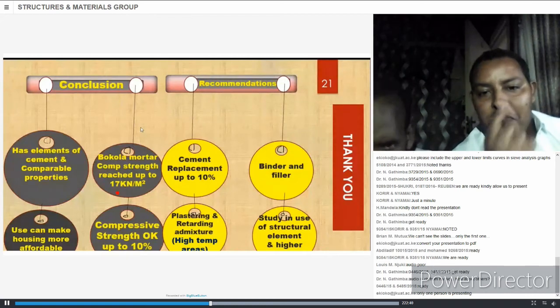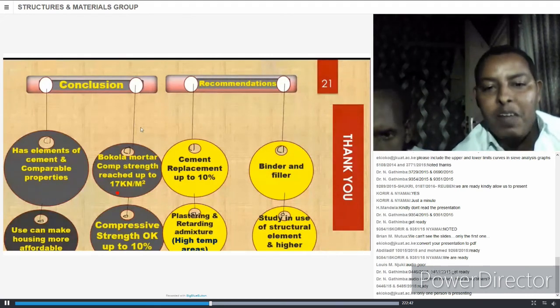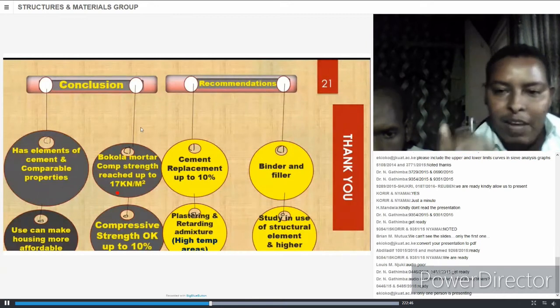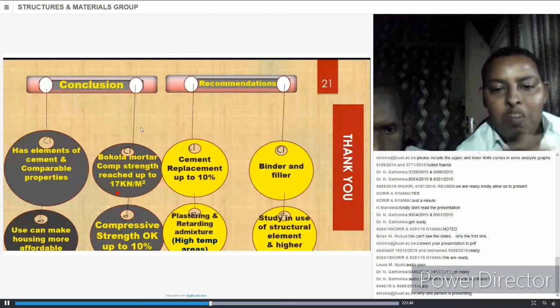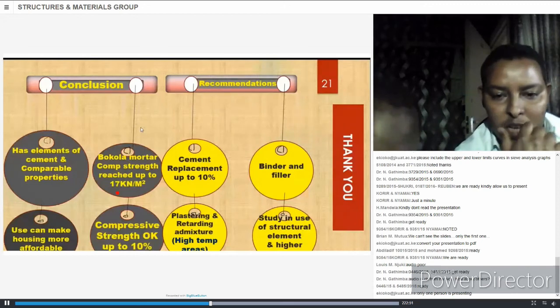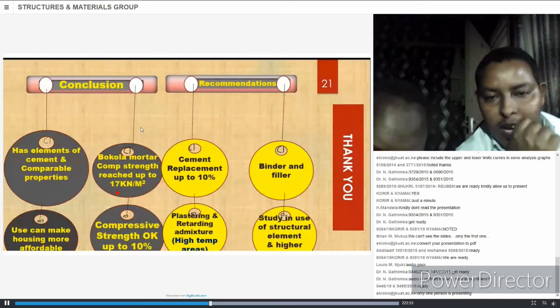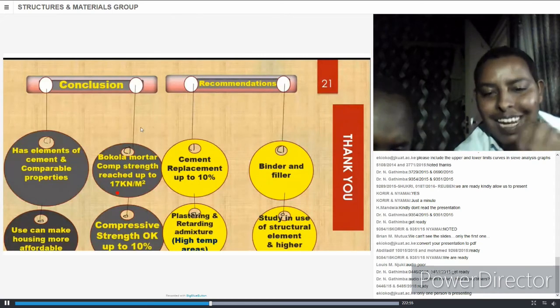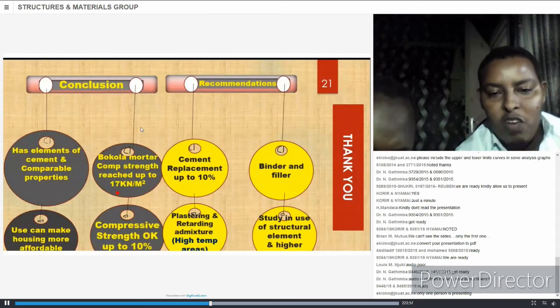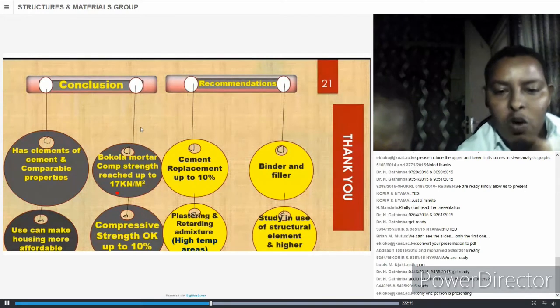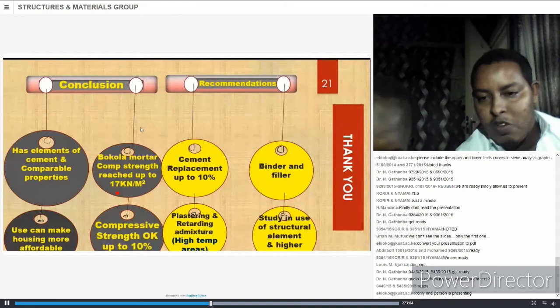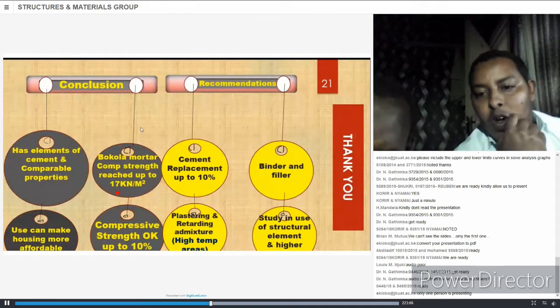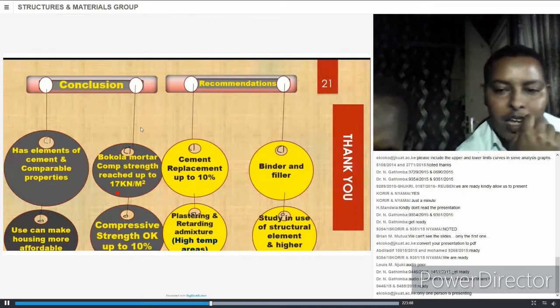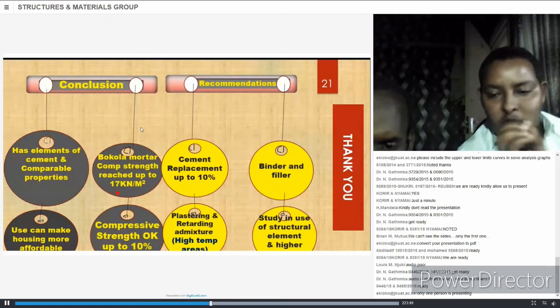On to recommendation, based on this study, we can recommend cement replacement with this material up to 10%. We also recommend it to be used as binder and filler because of the bonding effect that it has. Since people are already using it for plastering, we think it's okay to continue. We also recommend using bokola material as a retarding admixture, because this soil is found in areas of high temperature, to slow the setting of cement due to high temperature. We also recommend a future study for use in structural elements.